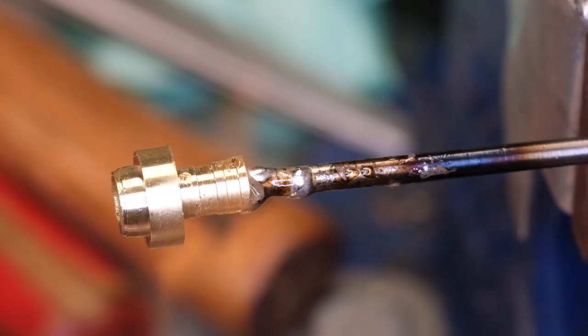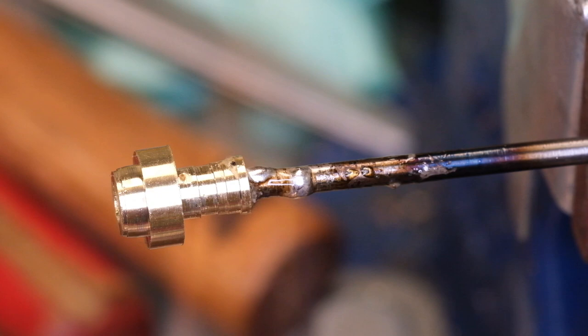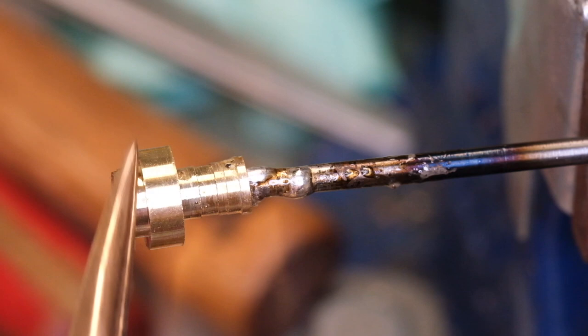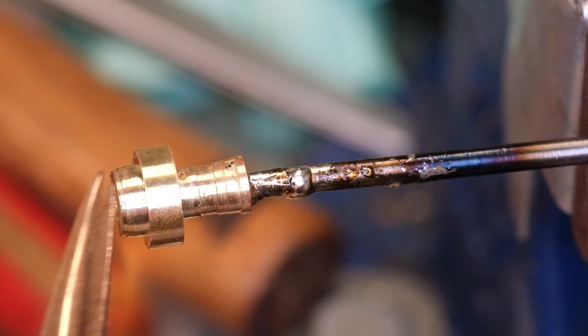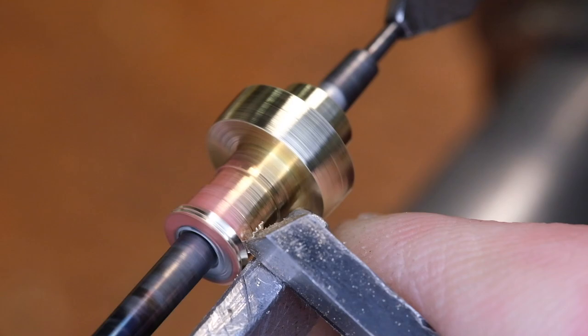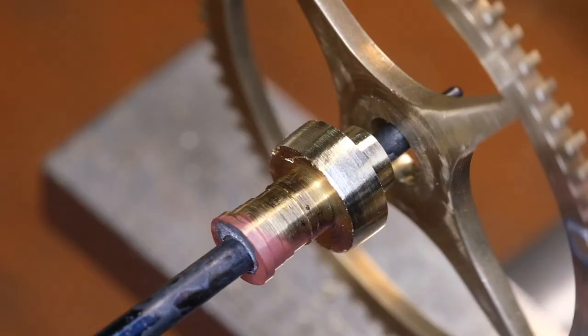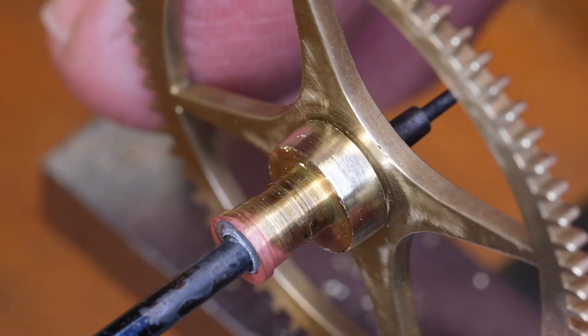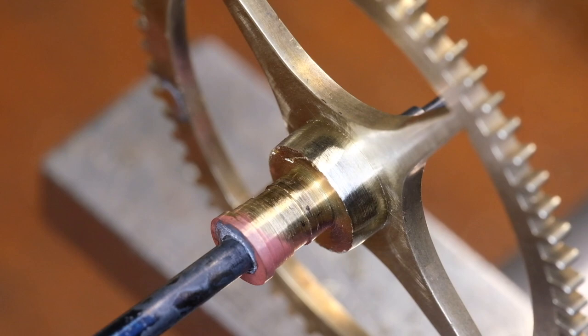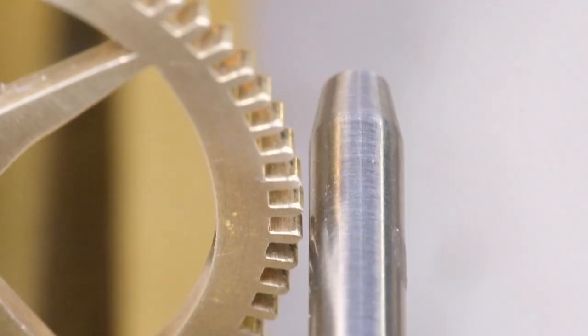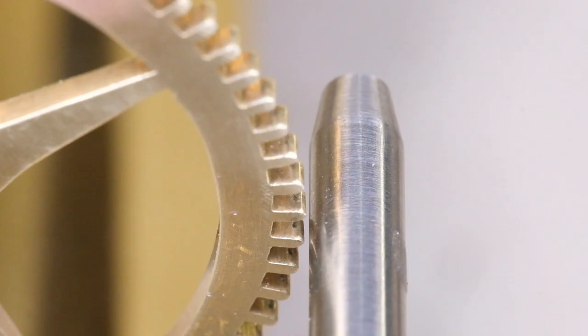The way that an assembly like this is made is that once the arbor is made concentric, then the collet is soft soldered in place with a relatively low melting point lead-based solder. That itself is then turned concentric with the arbor, then the wheel is mounted and riveted in place. And that's all great, until for whatever reason you decide to move the collet on the arbor because effectively it is impossible to get that collet and therefore wheel concentric and flat again. So the first lesson there really is never to move the collet on the arbor unless you know you're going to have to re-collet.